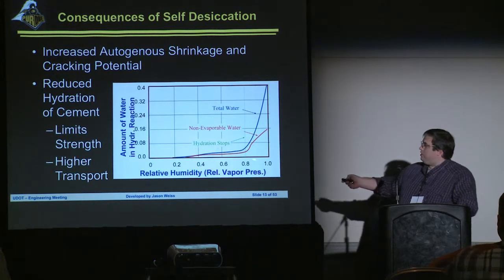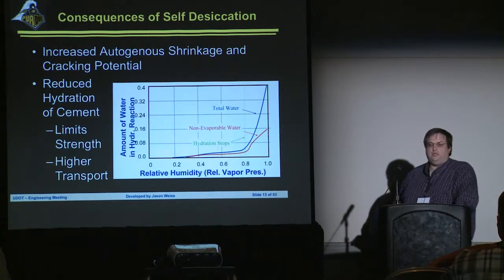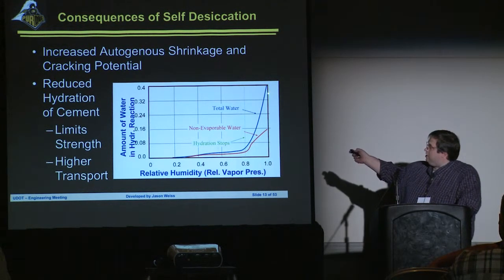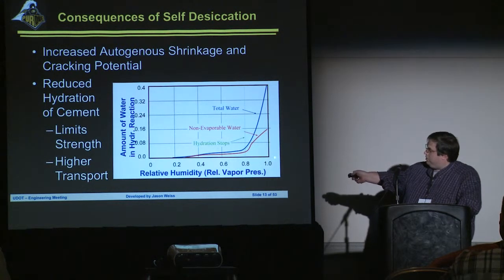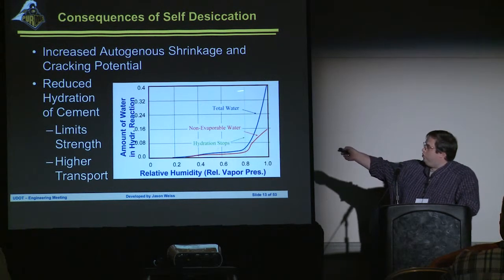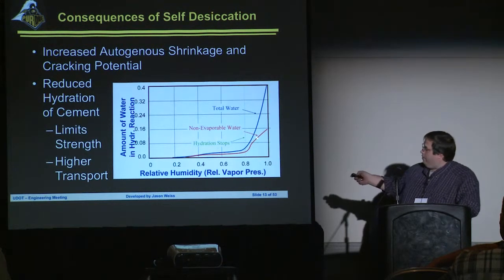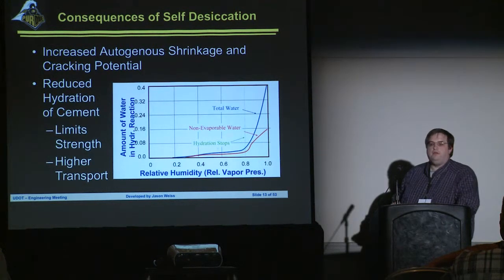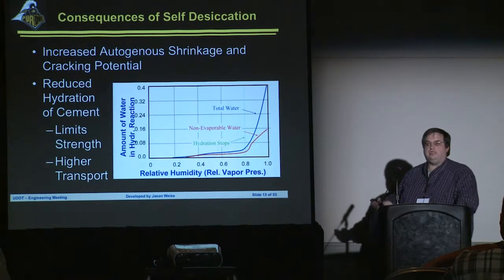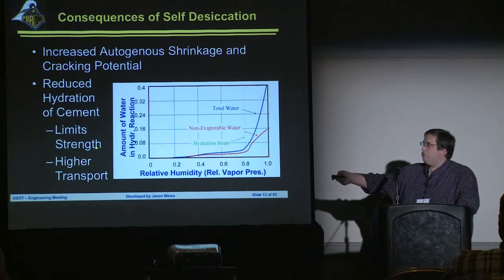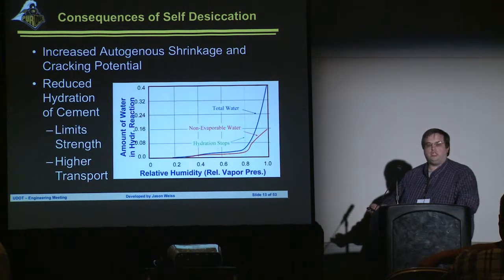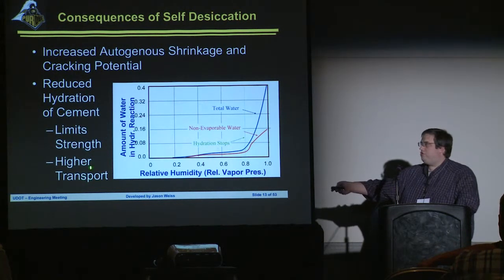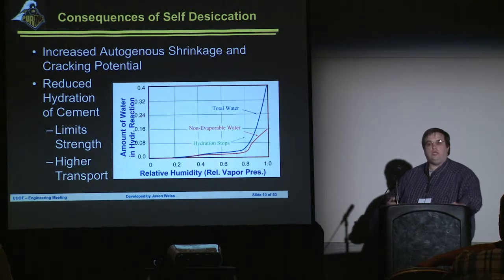Here you can see a pretty old chart that comes out of some work done at PCA in the 1940s that says essentially if you have 100% relative humidity, you've got a lot of free water, you get a lot of chemical reaction going on. However, as the humidity starts to drop, you start to drop how much of that cement can be reacting. So another potential consequence of self-desiccation is you're really going to limit the hydration reaction, which limits strength development and gives you higher transport because you can't fully disconnect all the pore network inside of the system.